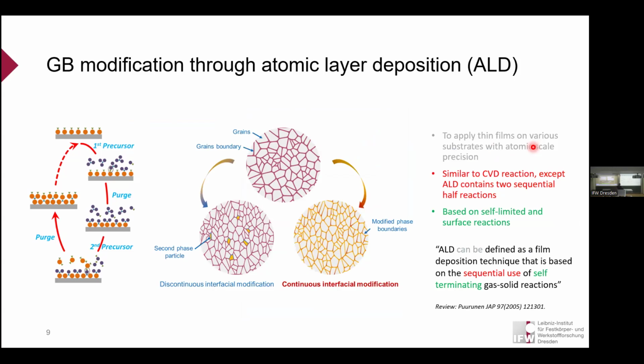If you are not familiar with this technology, a brief introduction: it's a deposition technology by cycles. You have two precursors, you purge and pump in one cycle, and then do the same process with the second precursor. This way, you can effectively coat these layer materials, layer by layer, in two half layers. And this is a self-limiting effect, so you can ensure that the growth is uniform, and the thickness is uniform and controllable.